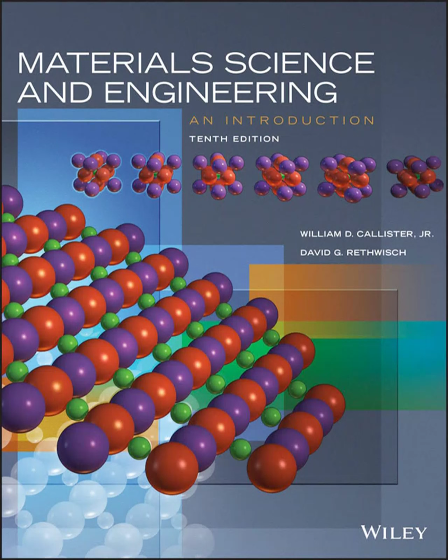Definitely. Second, and this is maybe the biggest factor, temperature. Even a modest increase in temperature can cause a huge jump in the diffusion coefficient. Think about this. For iron self-diffusion in alpha iron, going from 500 degrees C to 900 degrees C increases D by about 6 orders of magnitude. 6 orders. That's a million times faster. A million times. It's dramatic. Why? Because at higher temperatures, way more atoms have enough vibrational energy to actually make those jumps.